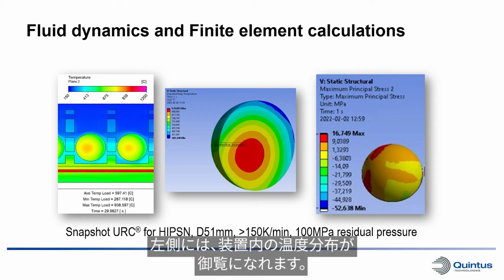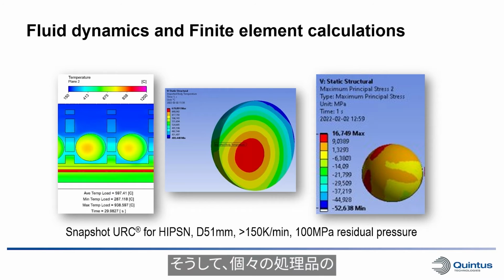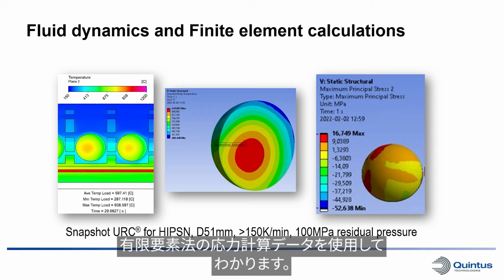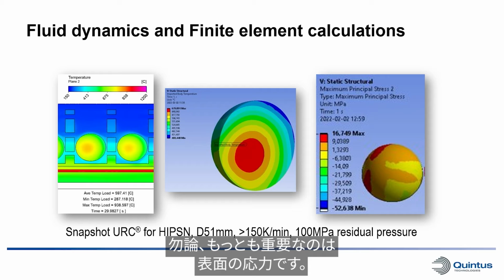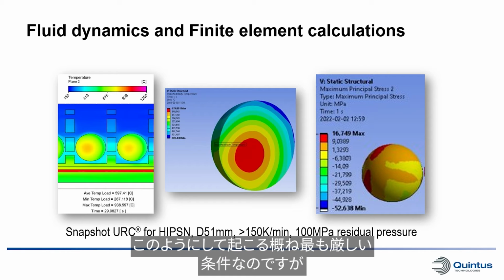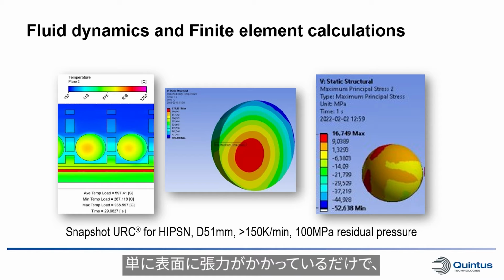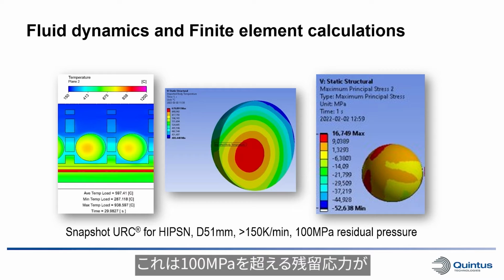To the left, you can see how the temperature will distribute in the system, and we can then from that look into how the temperature will distribute inside the individual component, using that data in the finite element calculation to find the stresses. And of course it will be the stresses on the surface that will be of most interest. And when running this cycle, which is more or less the toughest condition that we can get from this, we see that we just merely get compression stresses in the surface. Of course, due to that we have more than 100 megapascals of residual pressure in the system compressing the components.